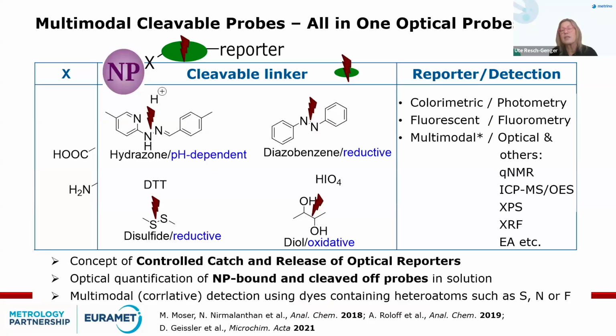So just to give you an idea about cleavable linkers, these are systems which are taken from drug release concepts, so the hydrazones, pH cleavable. What we really like are the disulfide linkers. There are also commercial systems like SPDP available. You reductively cleave the disulfide bonds and you can quantify the sulfur on particle. You can quantify the probe in solution. And you see here, thereby you can do a straightforward method validation.